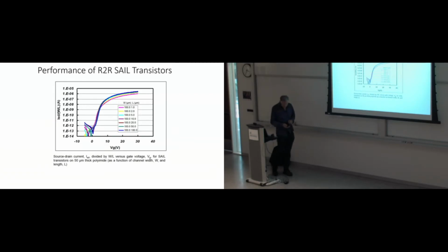And these are different transistors. You can see that's 2 microns right there, and so you can see how accurate the structures are that we can do. Here's some transistors. These are amorphous silicon, and this is the source-drain current divided by W over L. So ideally, if there weren't short channel effects, these would all be on top of each other, which they are for the 100 micron and 50 micron. When you start getting to 2 and 1 micron, you start getting short channel effects, not so much short channel, but contact effects. And that's why the current isn't quite as high as you might expect.